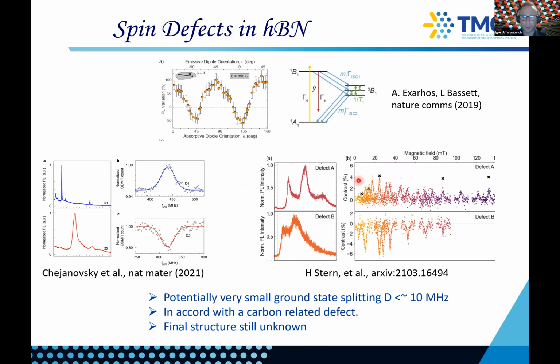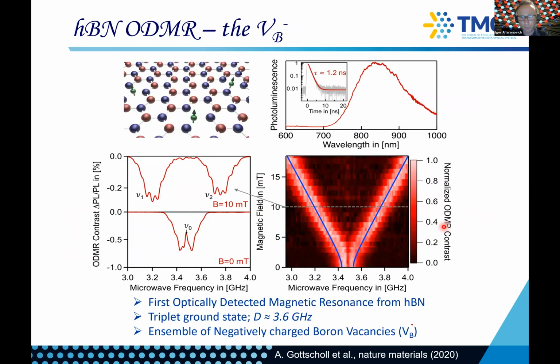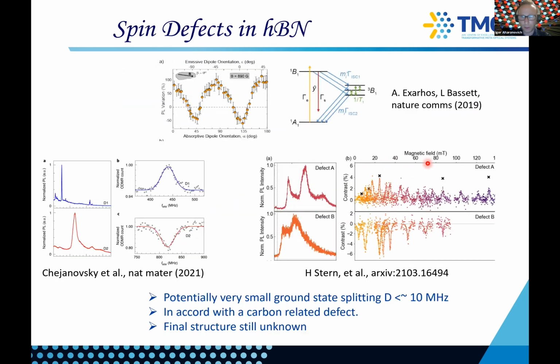So this is all at room temperature, and they also managed to replicate this positive and negative ODMR signatures. So interestingly, both of these results support these carbon-related defects, most likely a trimer, C2CB or C2CN, with a very small ground state splitting. So this was good, but it's still not a spin one system, because you can see that you increase your magnetic field, but the peaks don't split, they just shift.